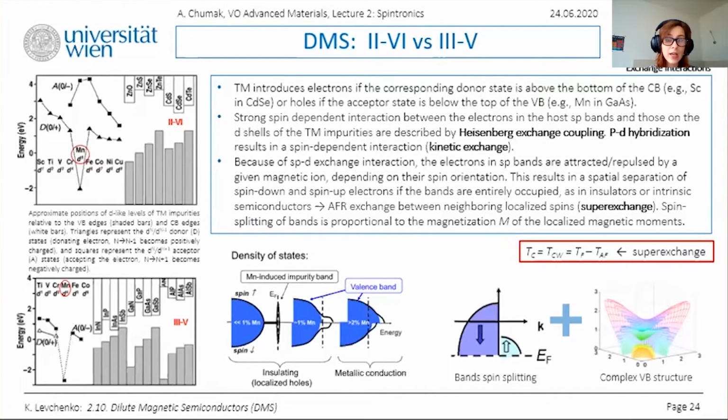Here the charged manganese pairs are ferromagnetically aligned by the holes, while RKKY corrections to this Zener model are required in a case of, for example, zinc manganese telluride, whose spins are electrically neutral. So nearest neighbors have electrically neutral spins and they remain in this anti-parallel configuration.